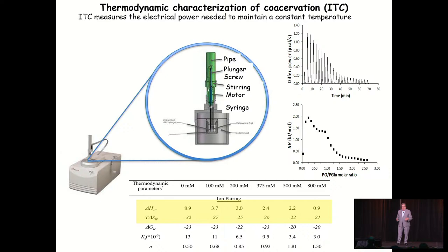And where does entropy come from? One obvious place is that if two macro-charged ions can neutralize one another, they're already entropically challenged themselves, they can liberate a lot of small counter-ions. And that produces some disorder in the system that leads to the entropy increase. But there are other things too, and Zhen-Gang Wang is focusing on some of these that have to do with hydration and the change in dielectric constant in the water. So stay tuned for a more precise comparison.